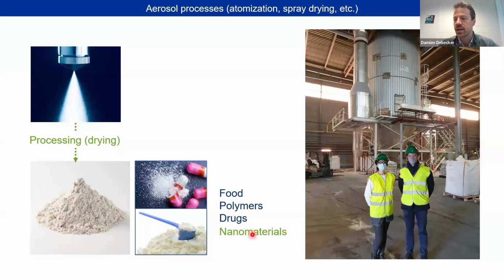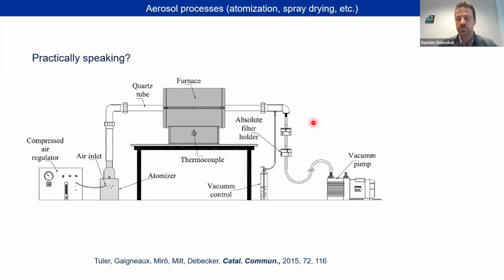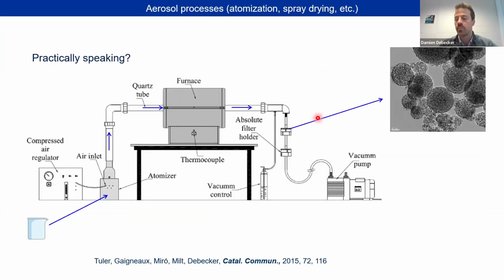And it can also be used to prepare nanomaterials. Here I'm standing with a postdoc of my team in front of a huge spray dryer that is producing tons of nanostructured alumina every day by spray drying. In the lab, of course, we don't use this kind of equipment. We use something that is much smaller. It's just an atomizer that works with compressed air, some tubings with a quartz tube here, a furnace, and filters. And what is happening is that we start with a liquid solution. We disperse it in the form of an aerosol. We pass it through a furnace, and we collect dry powders on those filters. So that's something you can build in your lab quite easily. It's not very expensive, and it's all the things that I'm going to show you afterwards. You can do that in this kind of equipment.